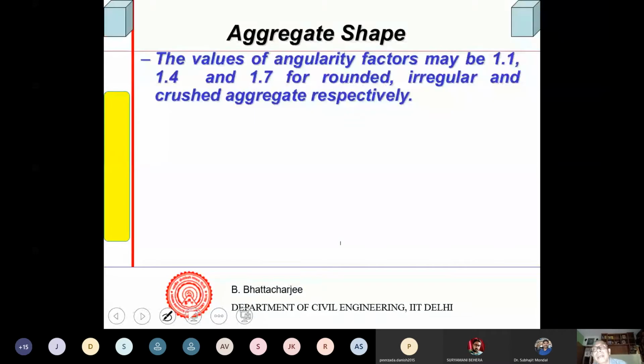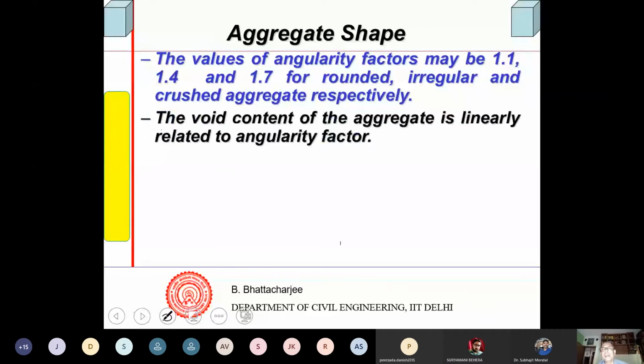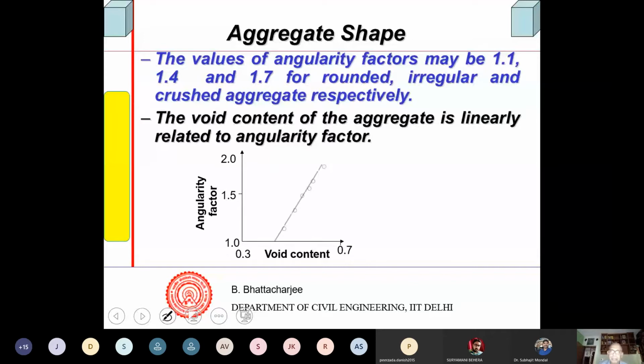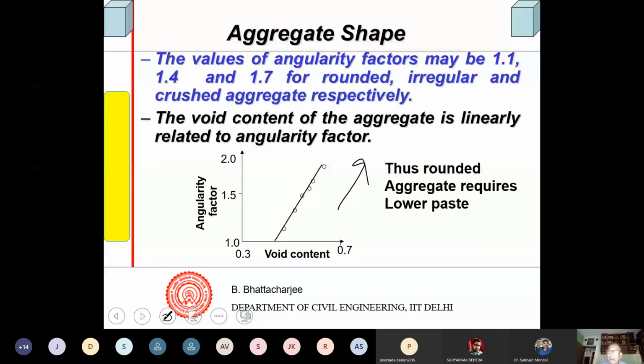So values of angularity factor are 1.1, 1.4, 1.7 for rounded, irregular, and crushed aggregate. And this has been observed by people. The void content of aggregate is linearly related to angularity factor. So void content will increase for a given type of packing. Thus, rounded aggregates require lower paste because they will pack better.